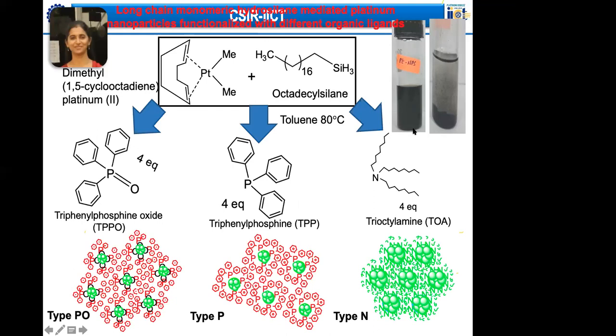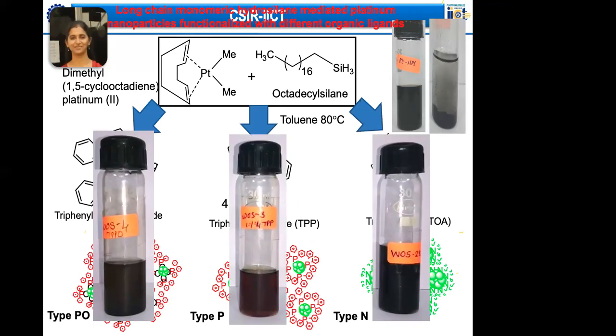But what happened within no time, they started to agglomerate and settle down like this, as you can see here, which means that the formation of platinum nanoparticles is happening, but they are getting agglomerated within no time. So when we try to use these kinds of ligands, we could end up having these kinds of colloidal solutions of platinum.